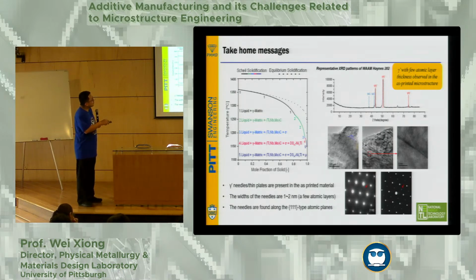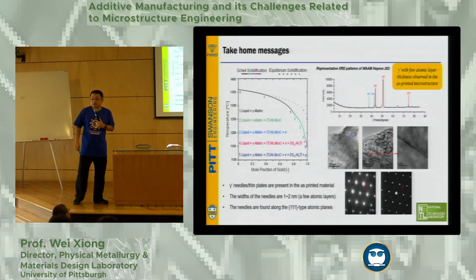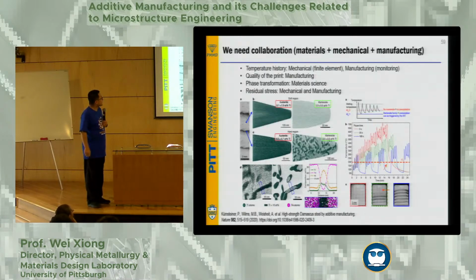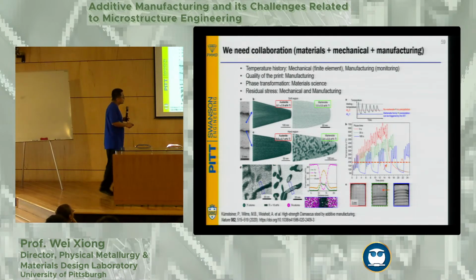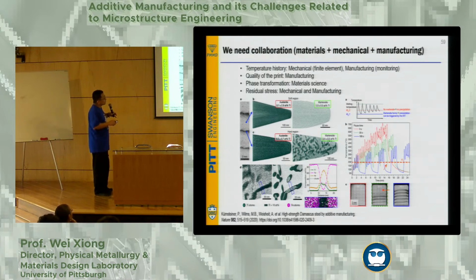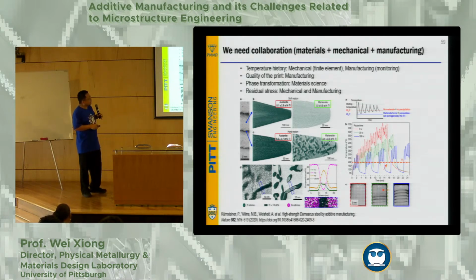That's one of the things we were also encouraged by when studying this Haynes 282. Once we finished our printing, after checking with the TEM, we do see some precipitation happening with gamma prime. That means there are some efforts we can make for this kind of printing optimization process. This indeed relates to one of the published Nature works by the Max Planck Institute, where they also utilized this concept to introduce in-situ precipitation of particles, like nickel aluminium, into one of the steels.